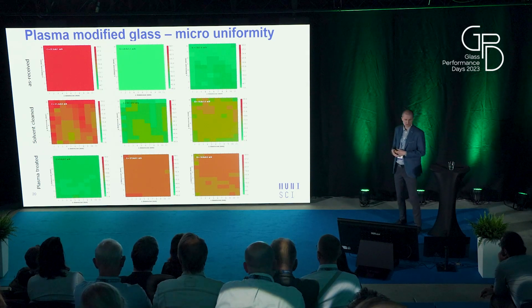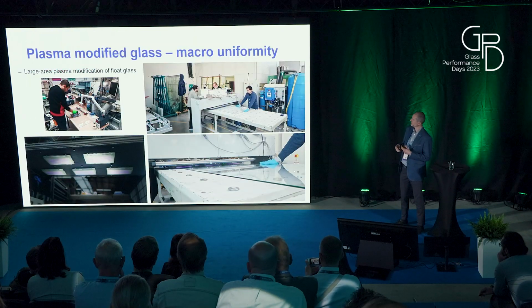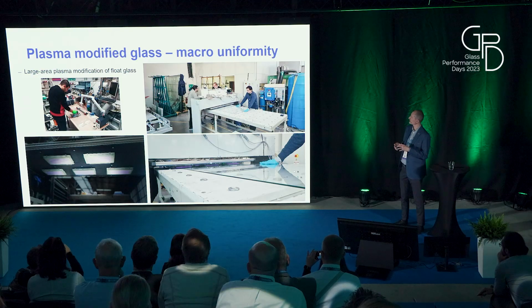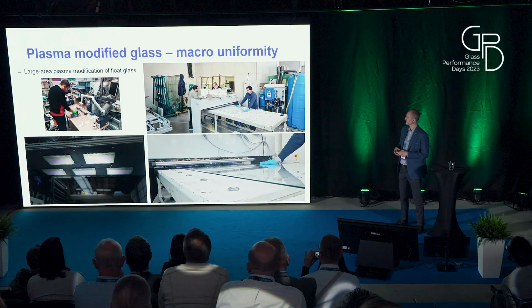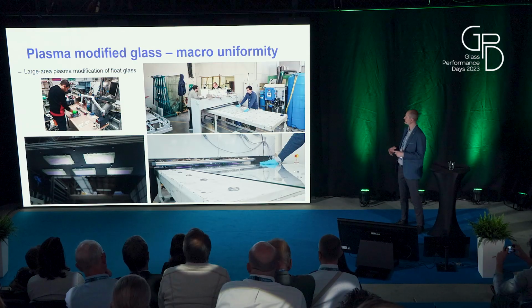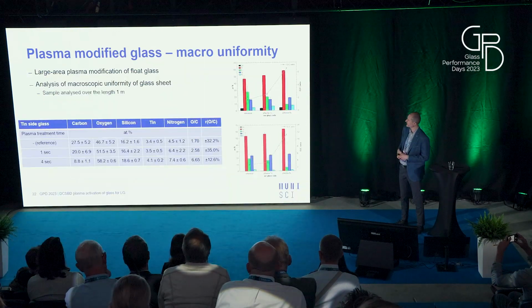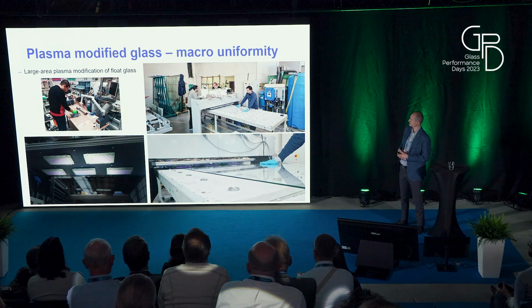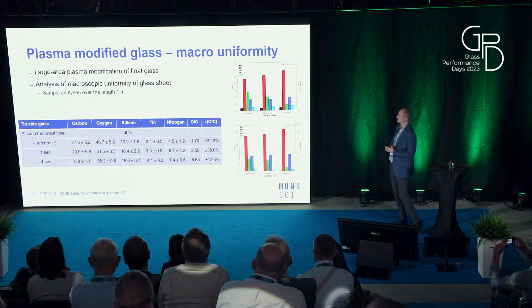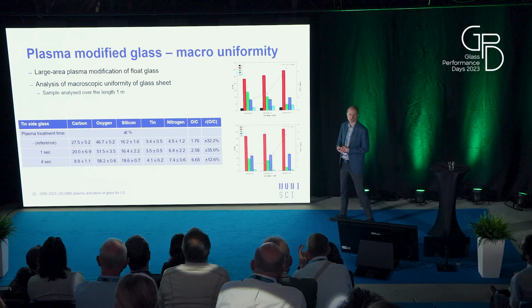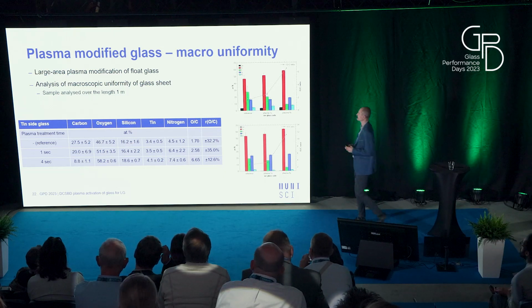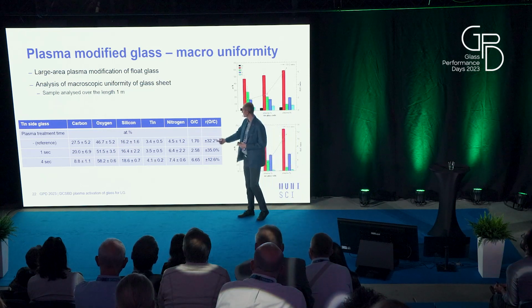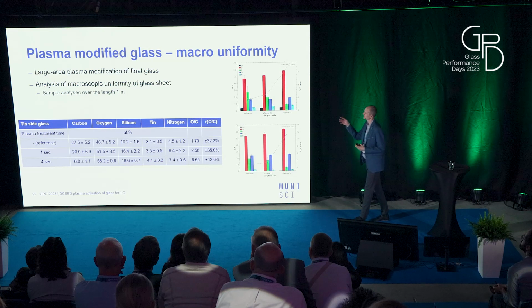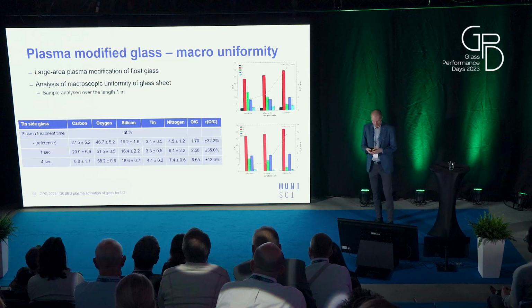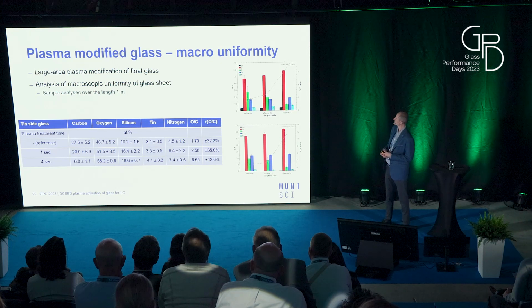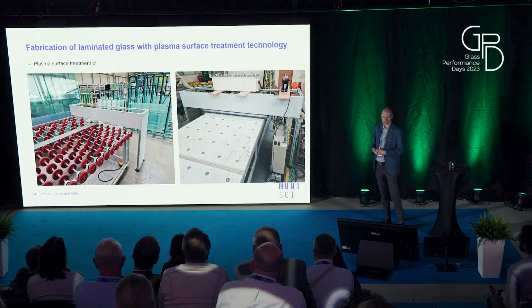We studied not only the micro-uniformity, but also the macro-uniformity. For this experiment, we treated really large samples of glass sheets using an array of 5 DCSBD units. And we analyzed, again, the variation of carbon, oxygen, and silicon. We can see that the variation of, for example, this oxygen to carbon ratio decreased from more than 30% to around 12, 13.